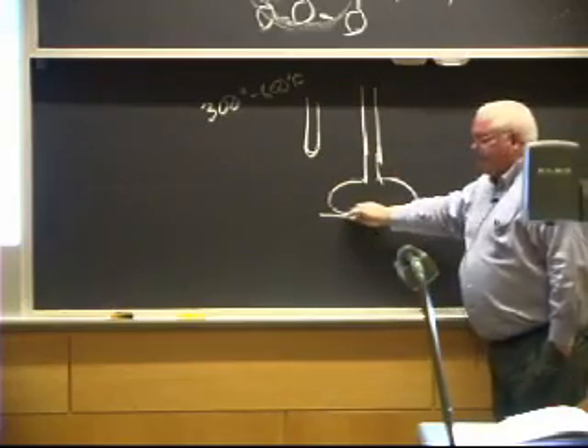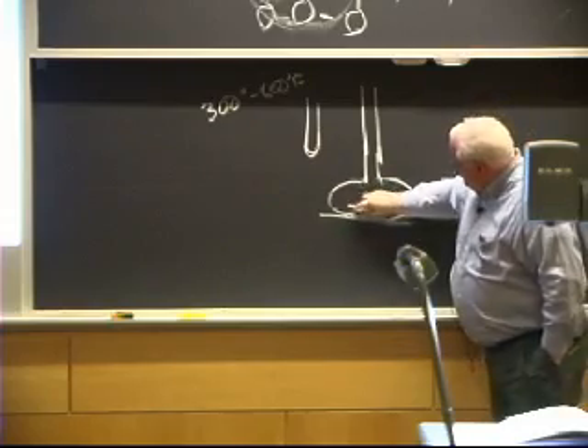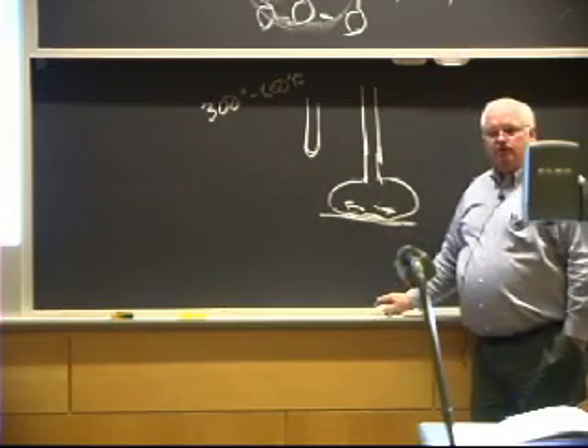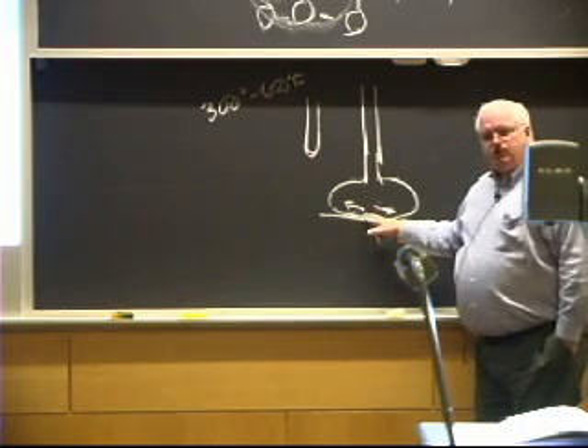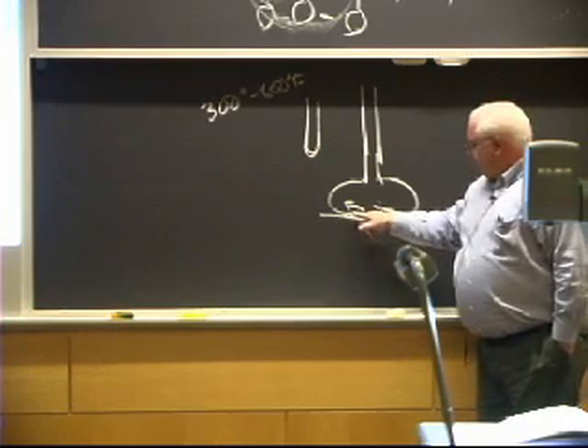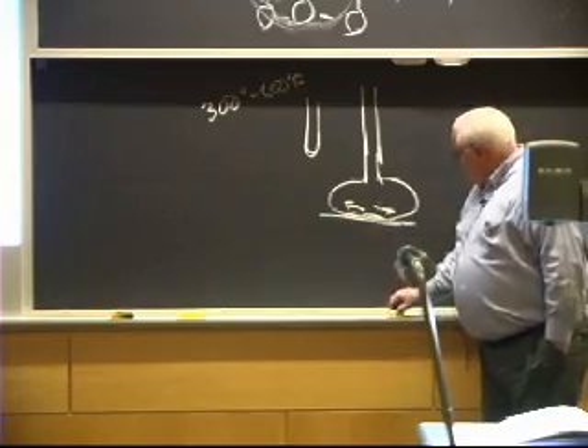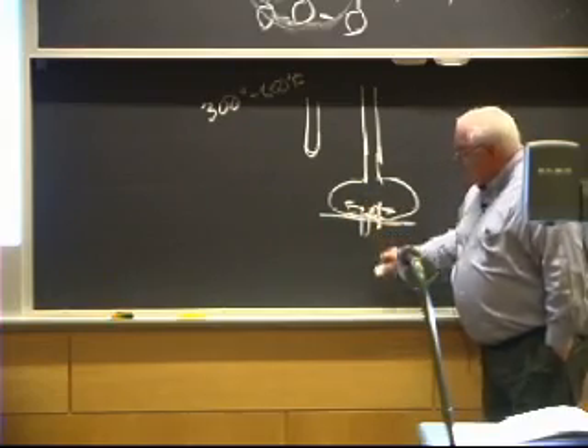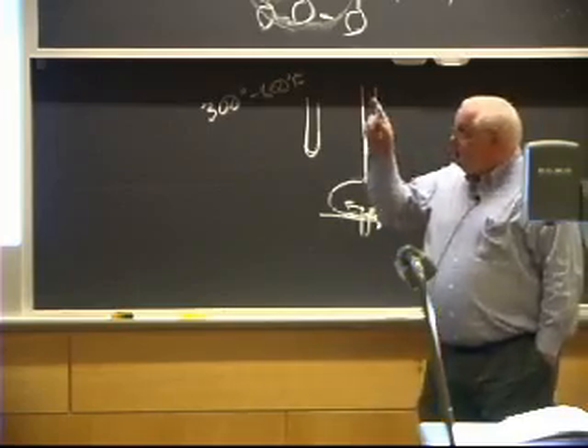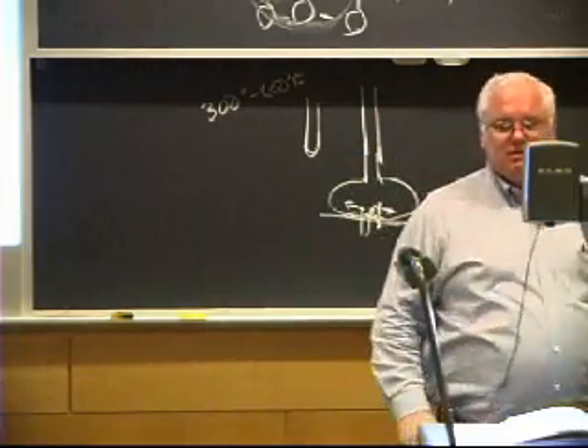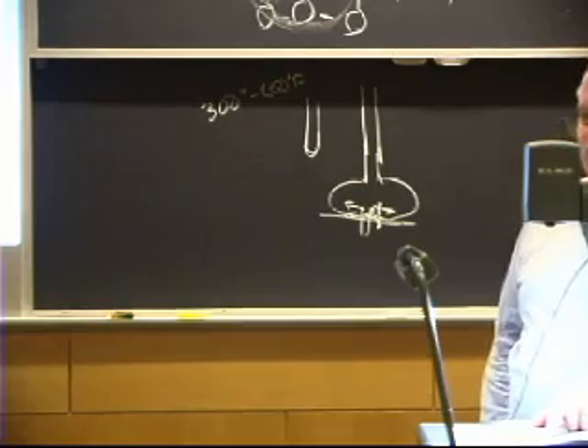And down here at this interface, I obviously get some shear as the material flows out on either side, right? So the shear scrubs the surface here. It doesn't scrub it much over here. So the only real bonded area is probably right there. Doesn't really matter. Those wires are typically, nowadays, on the order of 20 to 25 microns. A thousandth of an inch is 25 microns, so these might be 8 ten-thousandths of an inch across. And you make these bonds at about 7 per second.